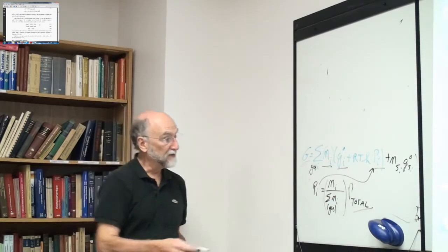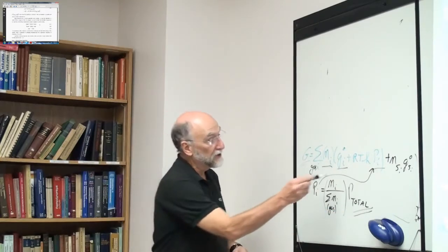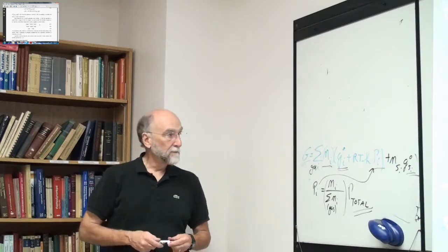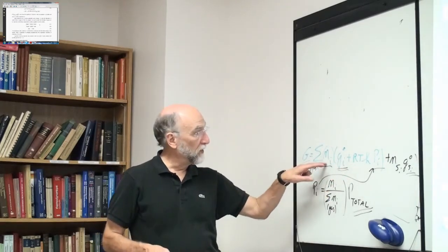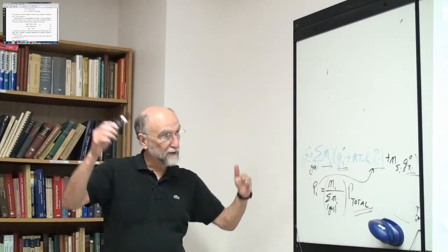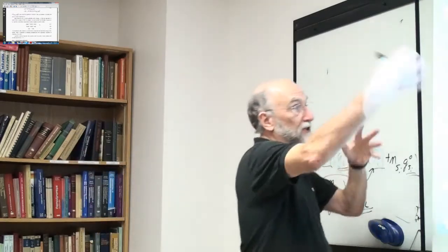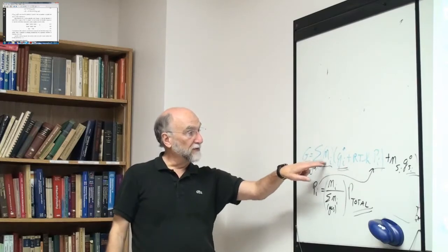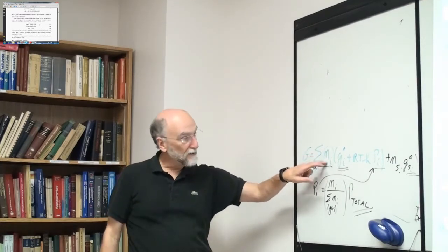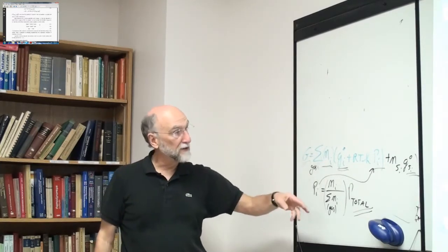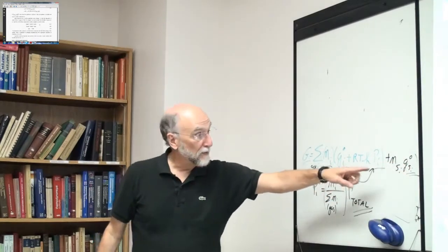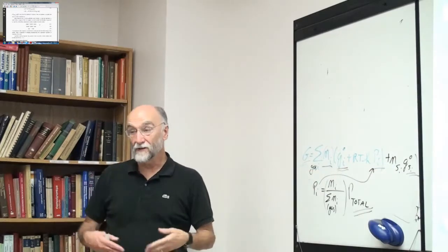Now if I have P total, I get the G0s from the thermodynamic tables, and I'm trying to find the number of moles of each gas. This whole thing is going to shift around until it reaches equilibrium. At equilibrium, you'll have a certain number of moles of silicon tetraiodide, a certain number of moles of SiI2, and so on, a certain number of moles of silicon. This could be 0, by the way, the number of moles of silicon could be 0, no silicon deposits.